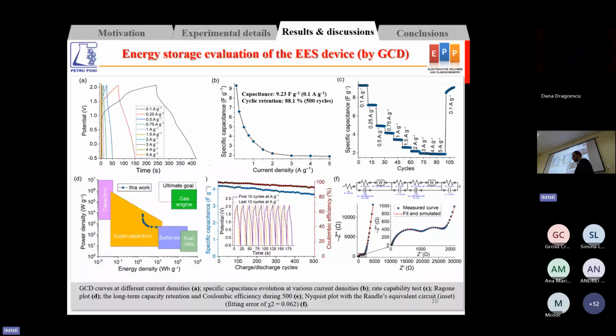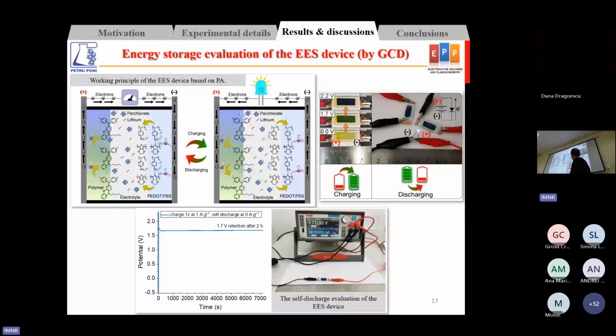Then we propose a mechanism during charging and discharging of the device. During charging, the polymer is oxidized and the electrons are moved from the anode to the cathode and neutralize the thiophene cycle. During this process, the lithium and the perchlorate ions move to counterbalance the generated charges. When connecting a load, the process is reversed.